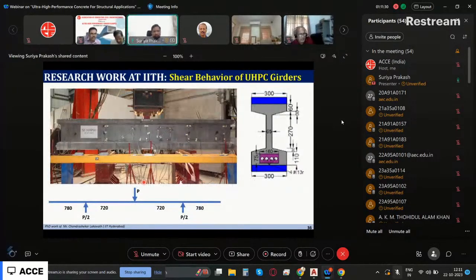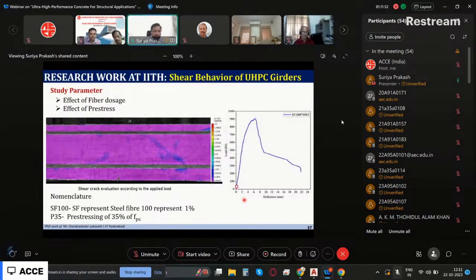Then throughout the world, we saw the behavior of bridge applications where we are using this, but how is this system behaving in shear? Because when it fails in shear, it is going to be a very brittle mode of failure. So to see how the system is behaving in shear, we tested several bridge girders like this, and then we evaluated the performance. So this is one of the tests. We tested in very heavy shear, and you will find that even after first cracking at about 550 kilonewton, the system was able to resist a lot of load.